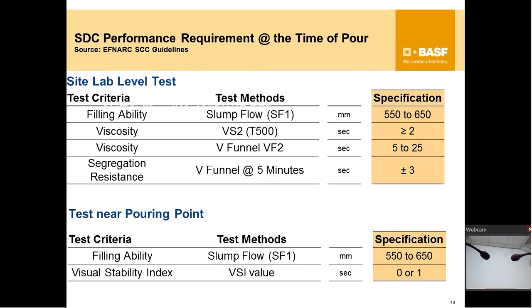I hope you know about the V funnel test. You have a V funnel with a trap door at the bottom. You keep the trap door closed, you pour this flowable concrete into it, and then you open the gate at the bottom and collect the concrete. You check the time for the concrete to empty the V funnel. That time in seconds should be between 5 to 25 seconds. Then there is segregation resistance. There are various ways of testing segregation resistance, but this is one test which we recommend. If you don't have too many testing instruments at a site, this is the basic instrument which you can have. V funnel test at 5 minutes.